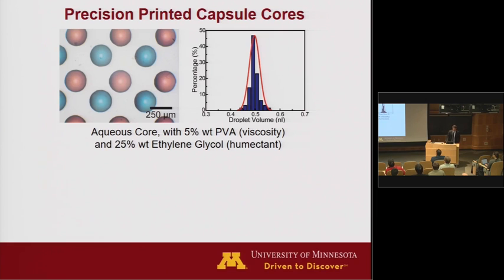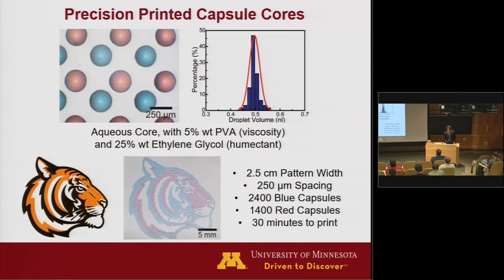And so again, we can 3D print these cores of some sort of biomolecule. Now, if you look at the volume of these cores, as promised, they're almost exactly half a nanoliter of volume from droplet to droplet, because the droplet that comes out of the printer is well defined. So you can see the tails of this histogram here don't even go to 0.4 or 0.6. It's actually a very precise control over dose that can be repeated from droplet to droplet in a multiplex way across a chip. And again, the multiplexing can be complex by virtue of the fact that we are using a 3D printer where everything is CAD designed here.